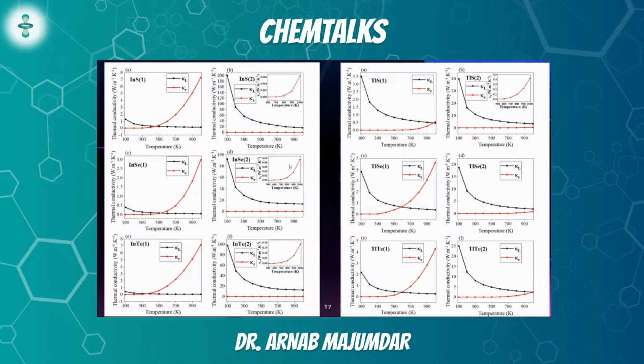So that means compared to the AX2 structure, which has been studied extensively, our structure theoretically gave us extremely low lattice thermal conductivities, which we also call ultra-low lattice thermal conductivity. Because for some of the values, they're actually even lower than 1. And once we increase the temperature, like if we go up to 1000 Kelvin or even 900 Kelvin, we see that they become very, very close to 0. It can't be 0, of course, but it's definitely much lower compared to 1. Whereas for the AX2 structures, they're always above 20 or 30, etc.